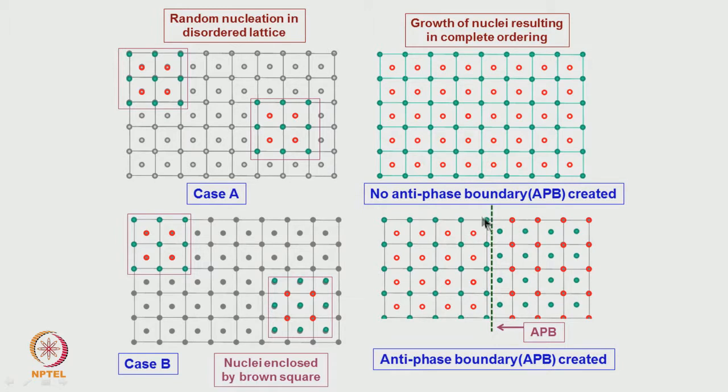From one region to another region, the lattice positions remain the same, but the atoms which occupy them change their position. So, if we go from here to here, since a specific atom changes, this introduces a fault vector. One in this direction is essentially from here to here. Since it is changing, the fault vector is going to be in this particular 110, or 100. That depends upon the type of crystal lattice which we are considering.